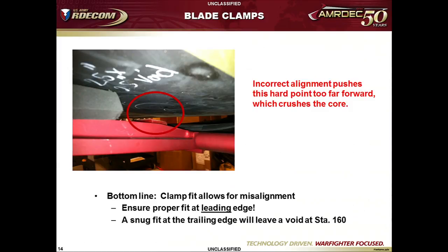If that rear clamp stays in place and it's just pushed onto the blade, that hard plastic piece crushes into the honeycomb. On this blade we had here, we actually already had the damage on there. So we clamped it down. After playing with this for a little while, we clamped it down and realized you could take it off and that clamp still be in place. When we pushed it on forward, you could hear it crush the honeycomb into the core. When we removed the paint, you could visibly see that the area was voided out. So I put that out there just as a caution. If anyone has any dealings with these blade clamps, or soldiers dealing with these blade clamps, make sure they follow the printed instructions that come with it.